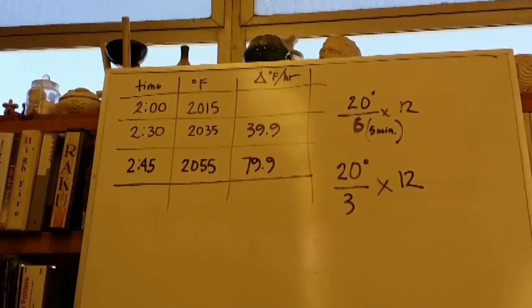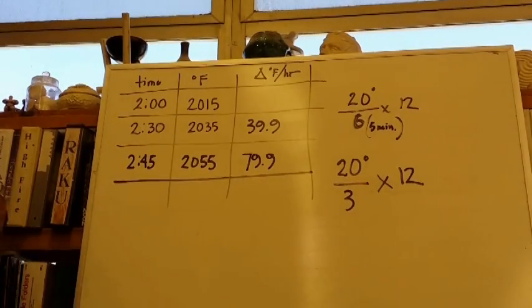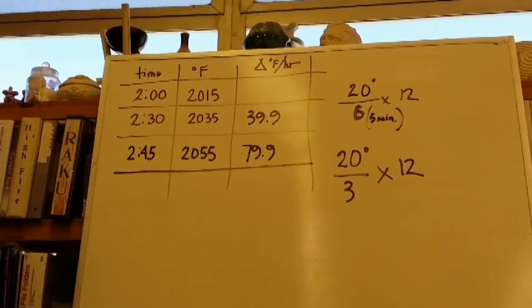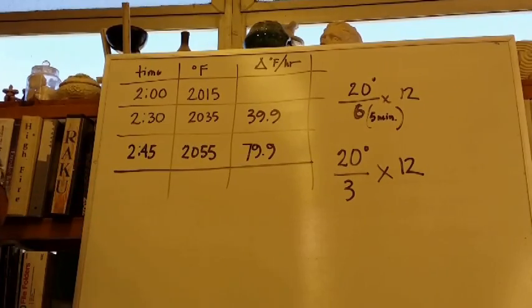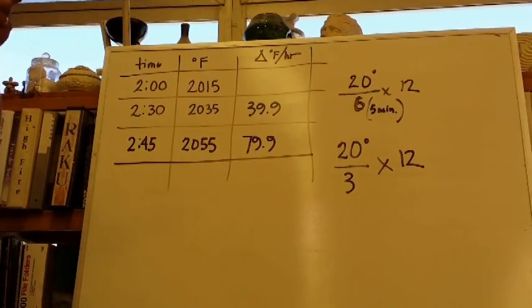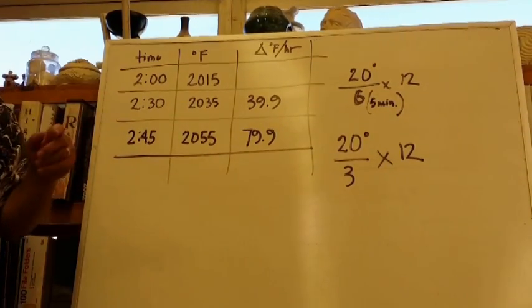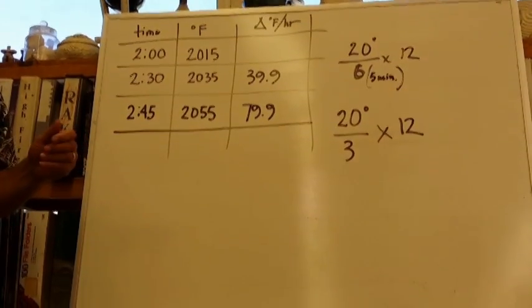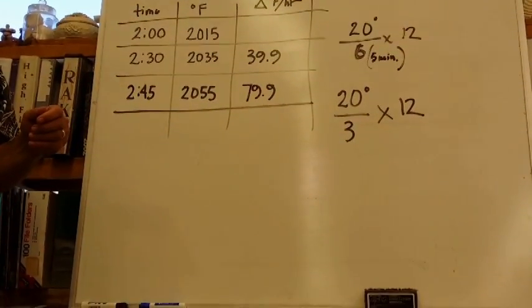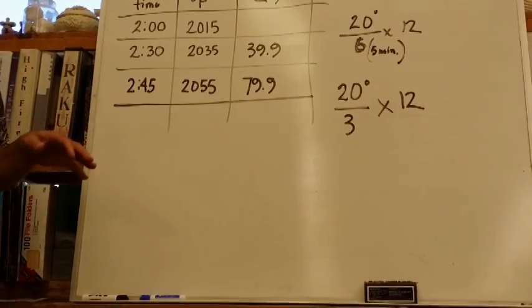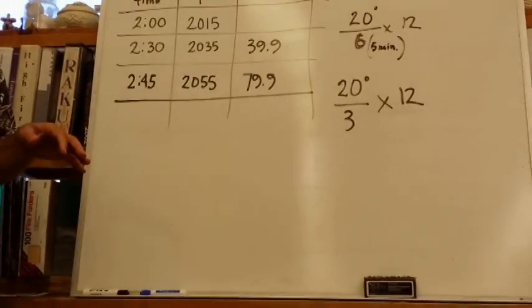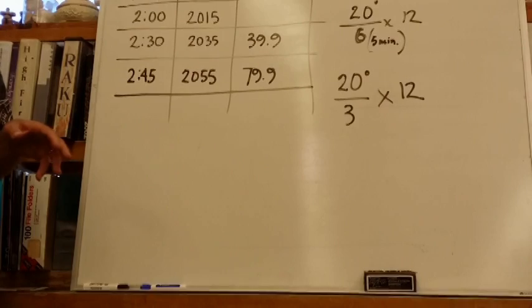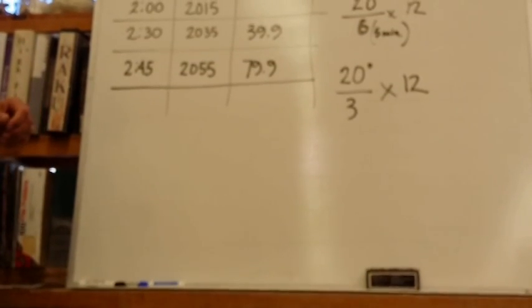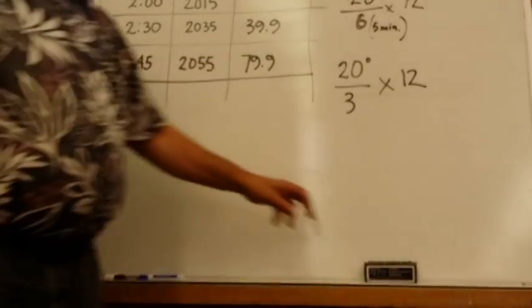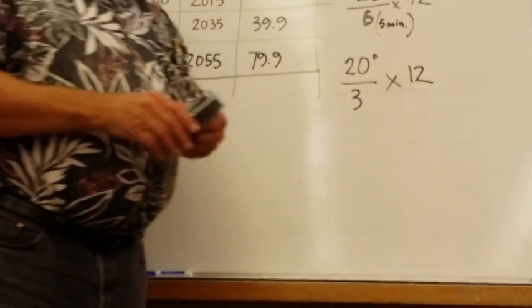And the longer the firing, oftentimes the higher the quality of the glaze surfaces. The longer the firing, the more we're spending on fuel. So it's a balancing act. When I first arrived here, I wanted to find out how fast that updraft kiln could get to cone 10. 3 hours. Wow. 3 hours for 2,300 degrees? That's amazing. Stuff that was in there wasn't worth keeping, but I found out what the kiln's potential was.